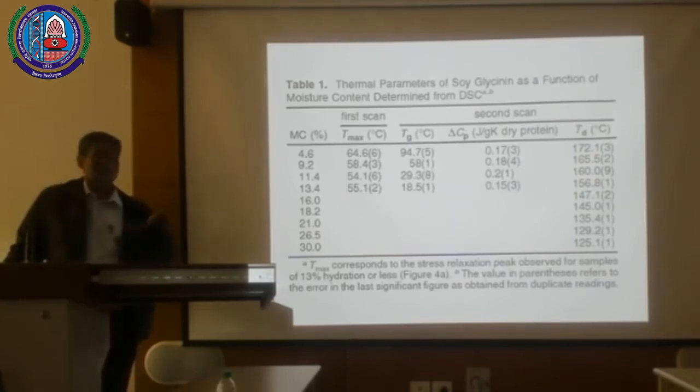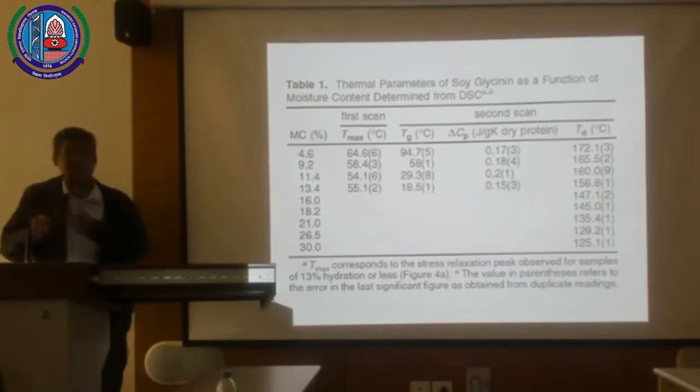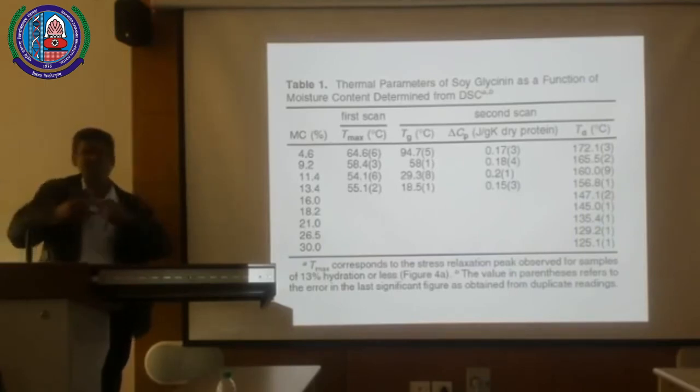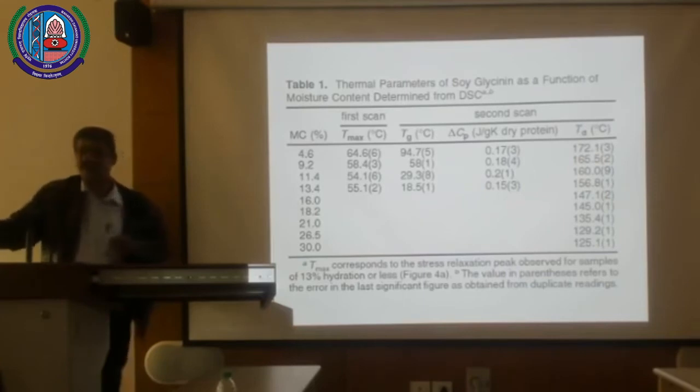It's a very good question. When you heat the sample, the reaction will take place over a very large window. Glass transition is very difficult to measure. It does not happen in a narrow window of 1 or 2 degrees, so you cannot take a pinpoint measurement for glass transition. It's happening over a 20 to 30 degree range. So we are integrating over 20 to 30 degrees of temperature. It has to start from some region and end at some region, and the midpoint is the glass transition temperature. Where it starts is called the onset temperature, and where it ends is called the endset temperature.